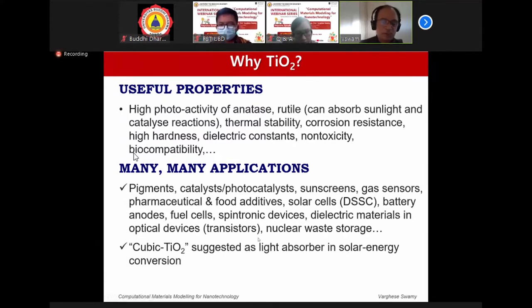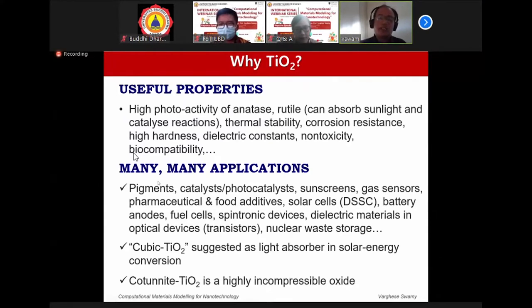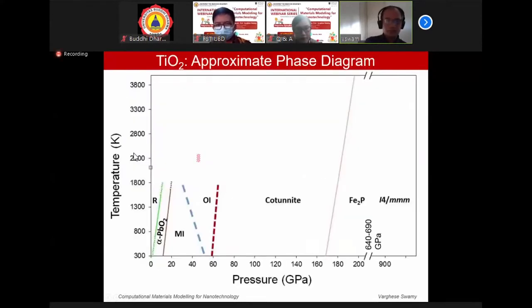In fact, I said I was looking for some missing phases. One of the phases I was looking for was the fluorite structured phase, so-called cubic TiO2. And then in this process, we came across a highly incompressible oxide structure called cotunnite TiO2. Cotunnite is lead chloride, but TiO2 can take that crystal structure. So we call it cotunnite TiO2.